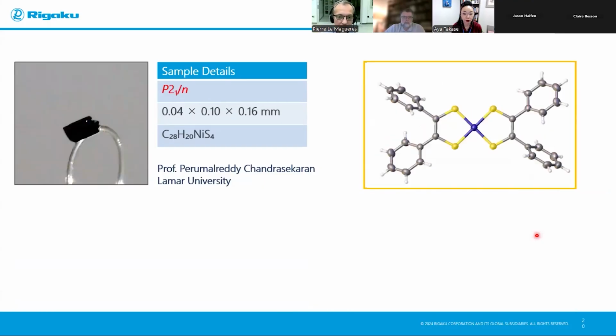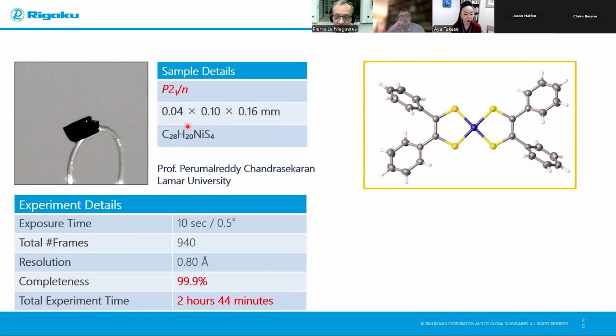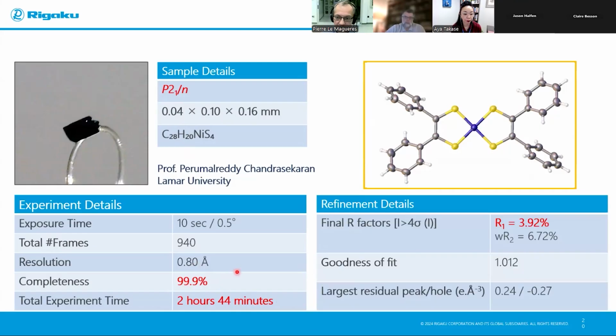The last two samples are of much easier crystals. So organometallic crystals. This one is a nickel coordination compound, again provided to us by Professor Chandrasekaran from Lamar University. P2 upon N space group, but again, a thin crystal of 40 microns. Now, because this is an organometallic compound, the diffraction was much stronger, data collection much shorter, so below 3 hours of data collection. Virtually 100% completeness at 0.8 angstrom resolution, and a beautiful structure just below 4%.